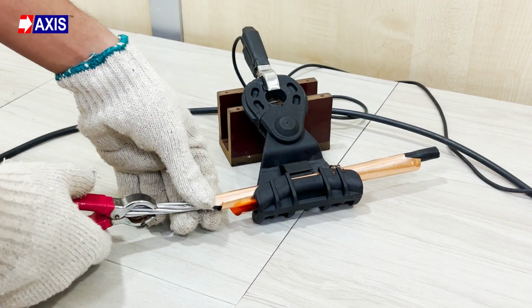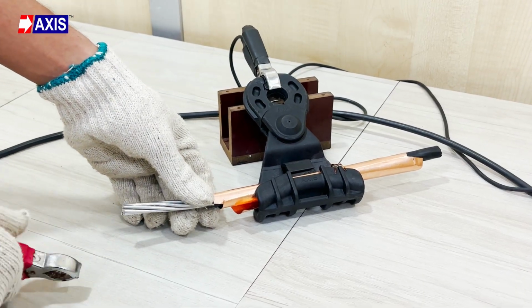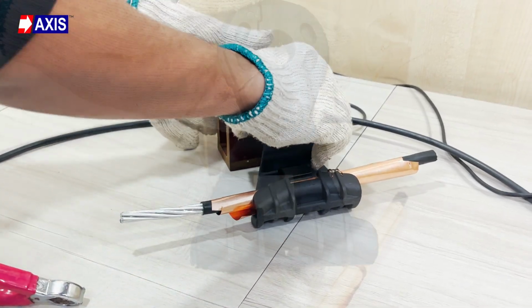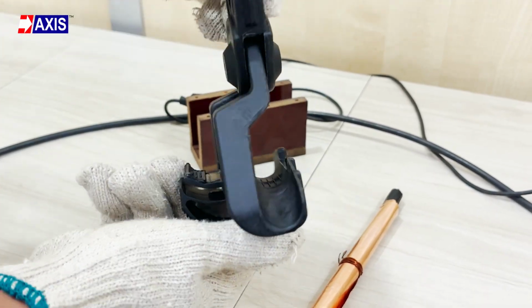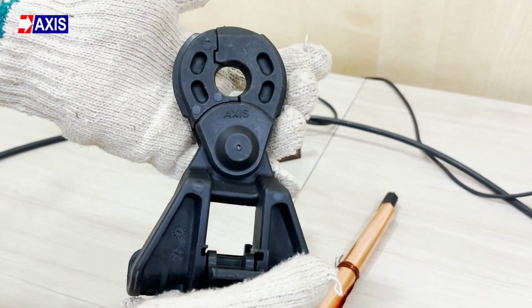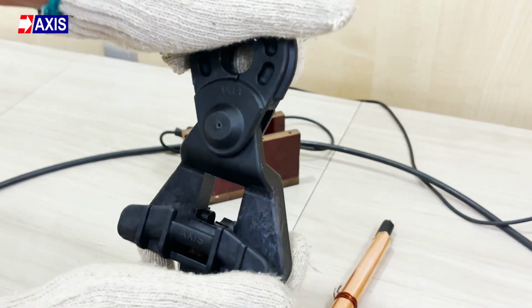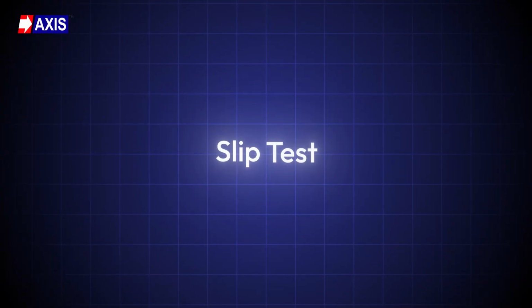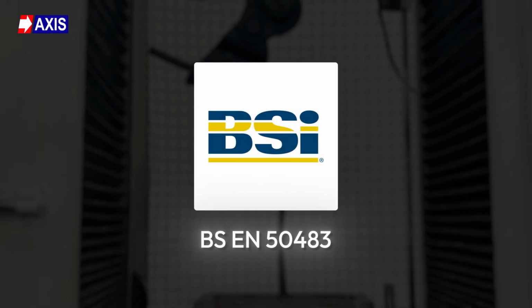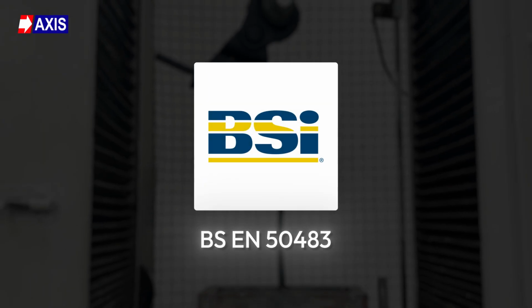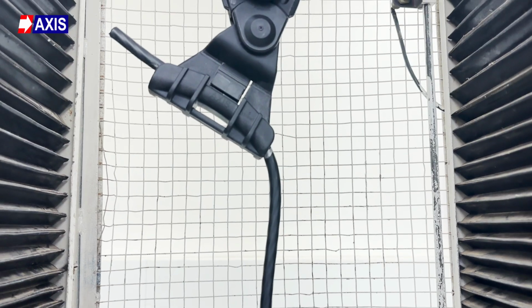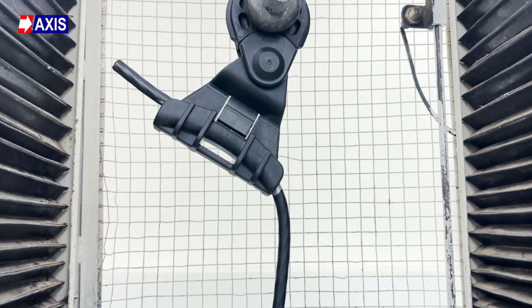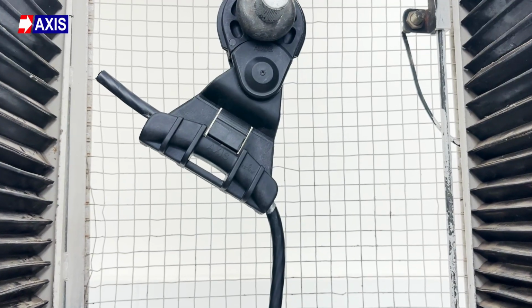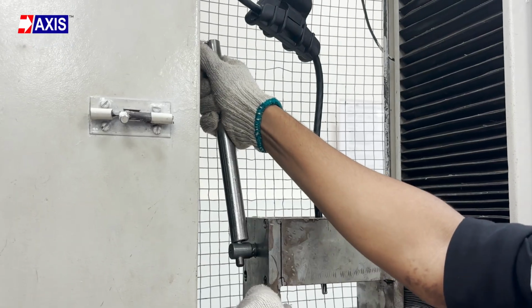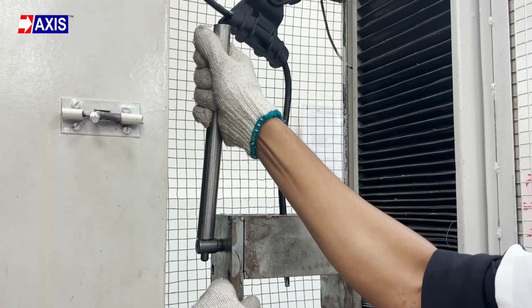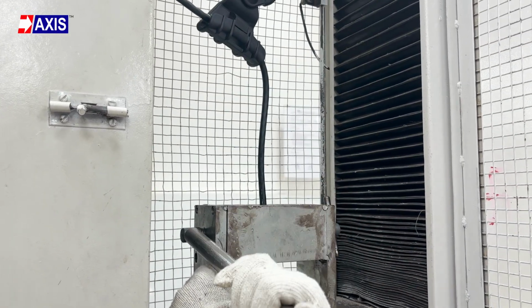As you can see, the Axis suspension clamp completed the test without any failure. This confirms that the clamp maintains dielectric integrity and electrical insulation under service conditions. Next, slip test as per BS EN 50483-3. This test verifies that your suspension clamp can securely hold the neutral messenger without allowing it to slip when it is subjected to mechanical load at normal ambient temperature.